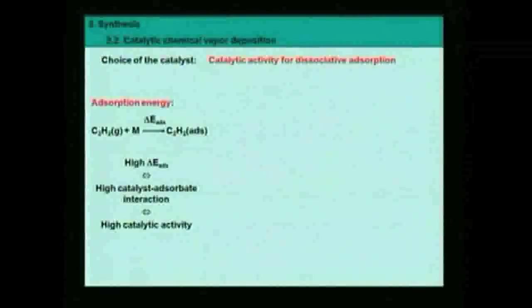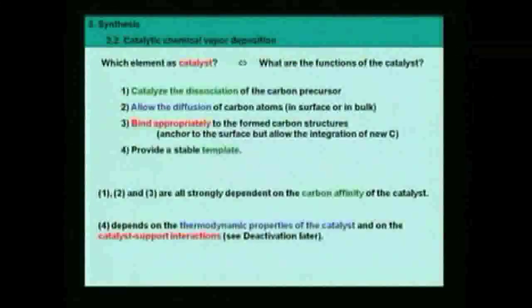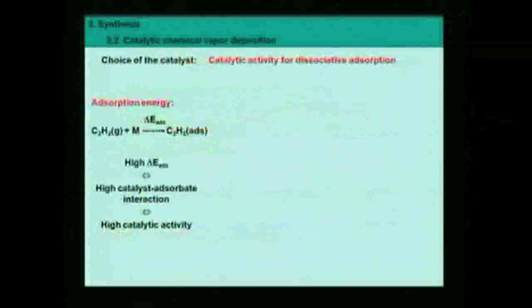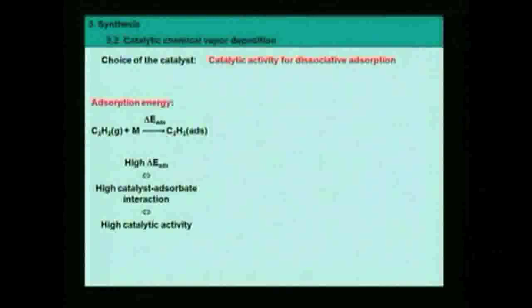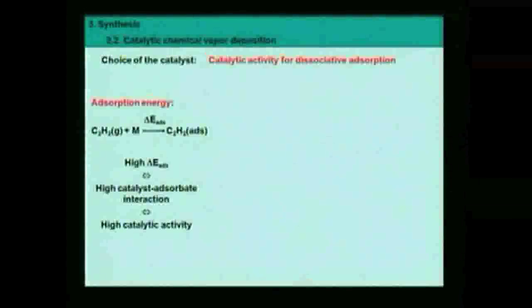Choice of the catalyst. So first point is to have a good catalyst for dissociation. As we already said, being a good catalyst, the essential catalytic act is to lower the activation barrier between the initial state and the final state. Just decrease this activation barrier. That is the energy of the intermediate state between initial and final states.